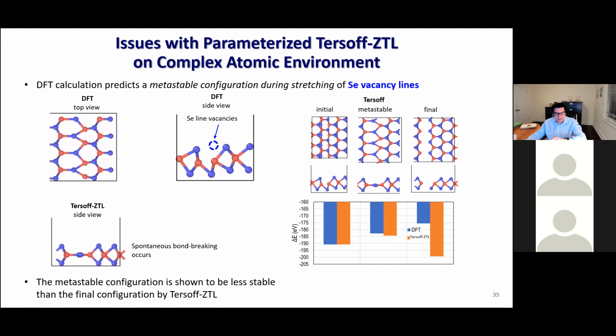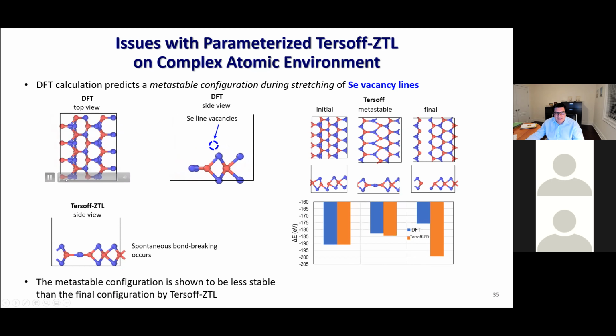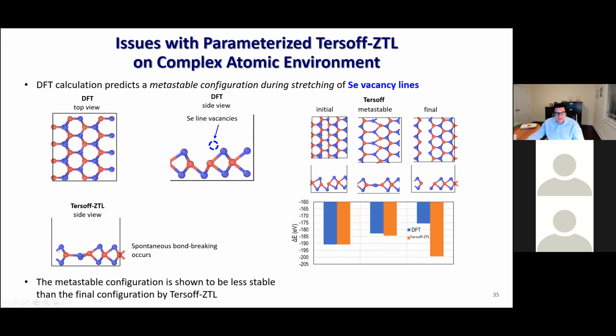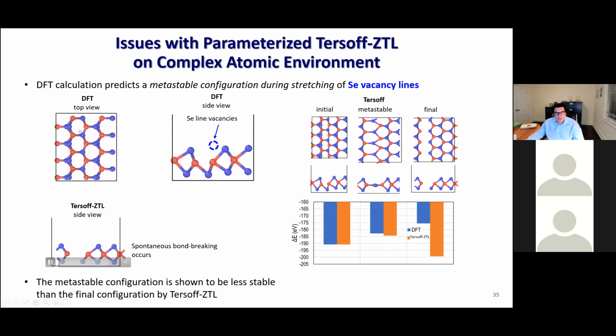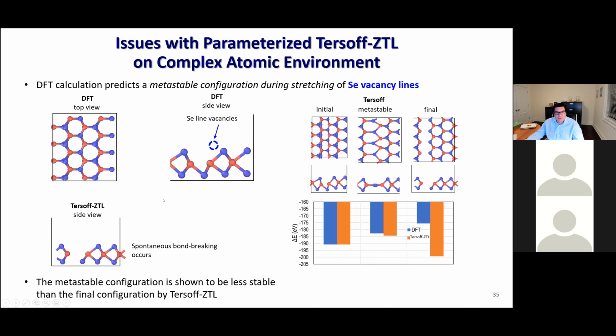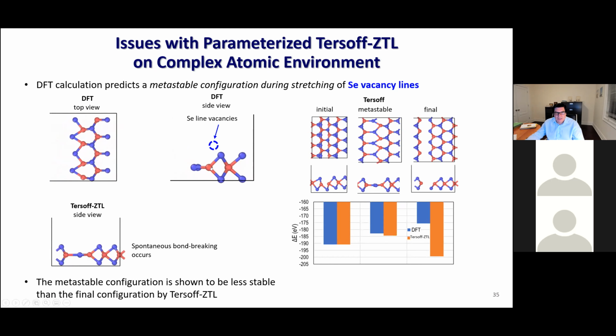The environment of the atoms is extremely broad and diverse. For instance, if you take a selenium vacancy, so you remove one selenium, you have two seleniums, one molybdenum in this hexagonal lattice. Suppose you remove one selenium, as is illustrated here, on the top, and what you see here, this is the DFT. It's with periodicity, a small number of atoms, but it gives you this breaking of the bonds. And look at the final deformation there.